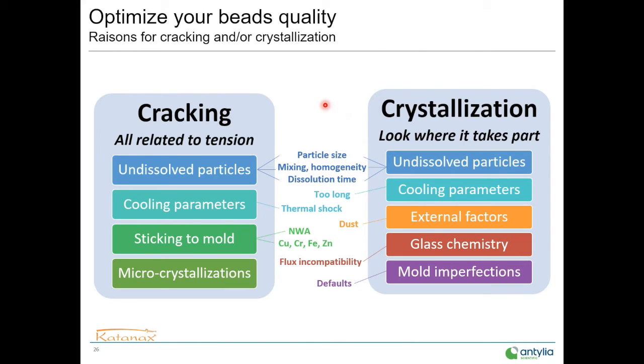Creating a piece of glass is not always easy, and you will have to follow some basic rules of glass chemistry. Two main problems can happen when you make a fuse bead, which are cracking or crystallization of your glass. Similar reasons can lead to the different problems. For example, undissolved particles can lead to cracking or crystallization depending on different factors. Cooling parameters as well can lead to cracking when we talk about thermal shock. Cooling can be a problem and lead to crystallization when it's too long and lets time to create nuclei and spread into a crystallization.